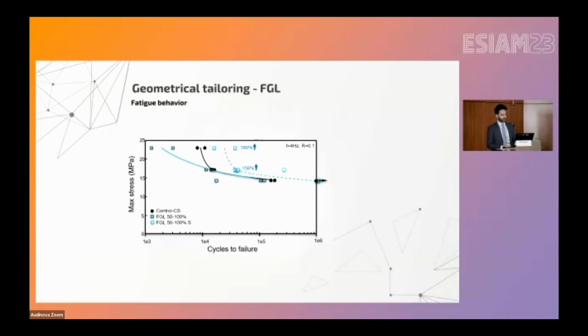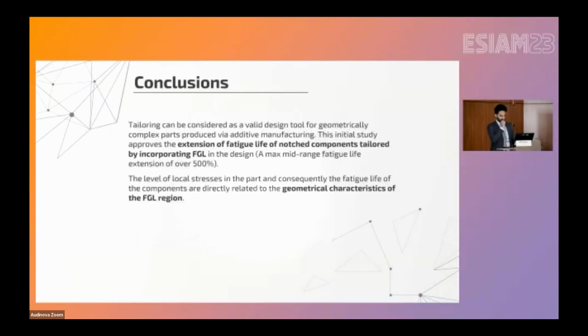In the second batch of specimens, we had 50% relative density. The improvement was less. Obviously, we are removing less material from the design, so we expected less improvement. Overall, this tailoring technique can be an efficient way for the design of our parts. We could clearly see an extension of fatigue life in the mid-range of up to 500%.